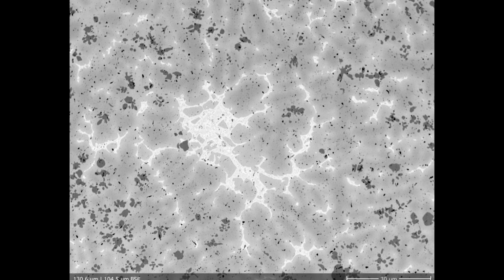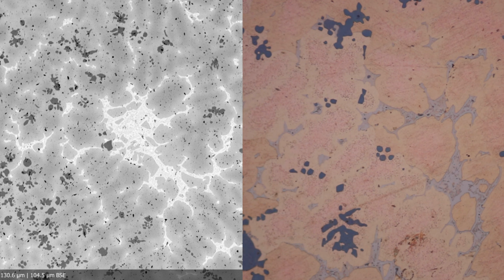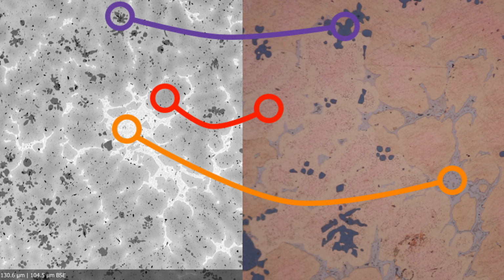As you can see, the crystals are clearly cored, which means that the composition of the core and rim is different. And to prove this, I need to employ another method, electron microscopy, which will provide us with information about the chemical composition. This is a typical example of an image from a scanning electron microscope. If you are having a hard time linking those phases together, here is a little help.